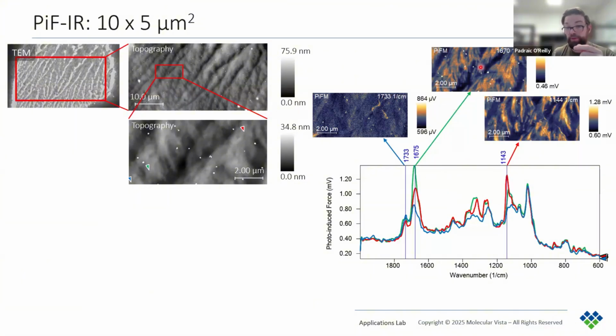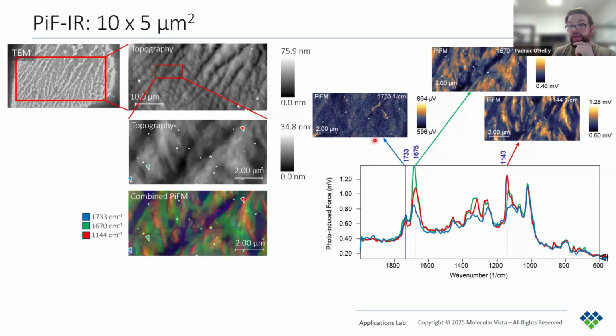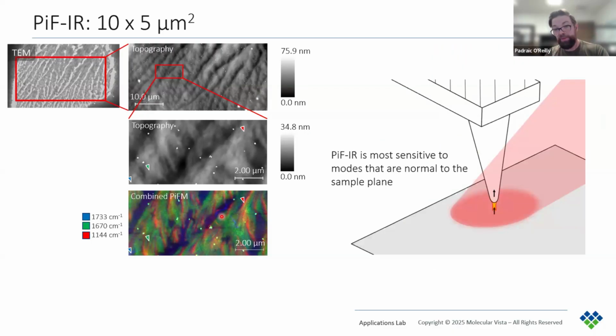Now, we've also taken PiFM images at these wave numbers. And then when we combine these, we see that they mostly highlight different regions, different locations. So this seems to be indicative of different crystal orientations. Now, the reason that PiFM can see this is the laser light that's used for PiFM is p-polarized with respect to the surface, and therefore it's along the tip, like with these arrows are showing. So PiFM is most sensitive to modes that are normal to the sample plane. So that is why PiFM can show variations in molecular orientations, especially in the rigid orientations of crystals.